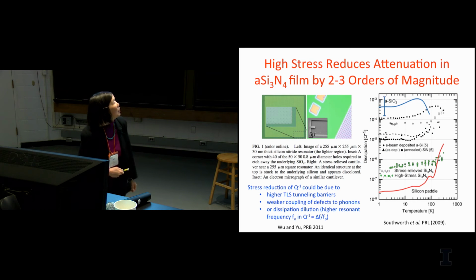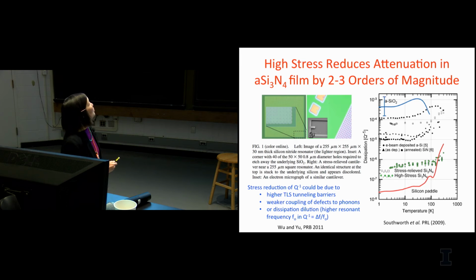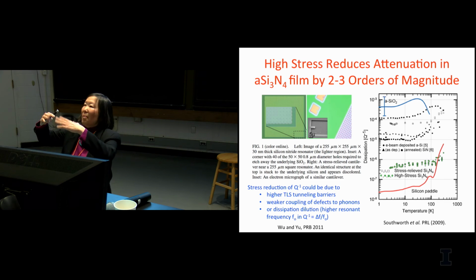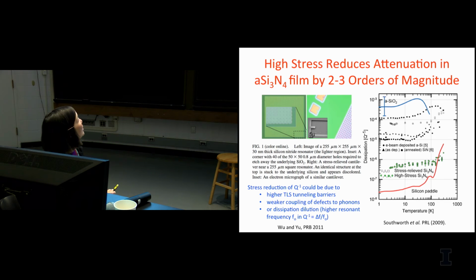There's also some work coming out of Jeevak Parpia's group where they took thin films of silicon nitride, again amorphous, and they make a drum head. So this is a high stress system, and they find that, okay, up here, 10 to the minus 4, 10 to the minus 3, this is where glasses are. Three orders of magnitude lower, the green points are where you have this high stress internal friction. If you don't stress it, if you make a cantilever like a diving board, the internal friction is still less than what you see for glasses.